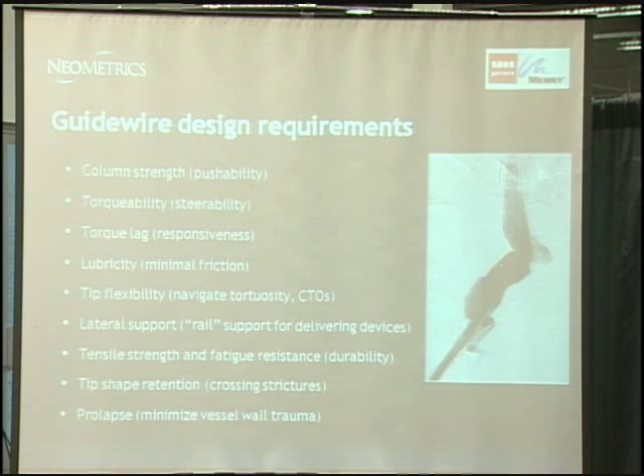Torqueability is also a critical factor. Given the softness of nitinol, its torque properties are not as good as stainless steel, and it has a tendency to build up a lot of torsional energy, which when navigating through a very tortuous path, it will build up energy and then release, causing a very severe whipping effect. And we wanted to eliminate that property of binary nitinol in this new material as well.